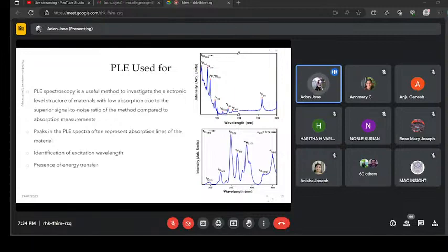Actually, from photoluminescence excitation spectroscopy, the first thing that we can interpret is that we can identify the excitation wavelength. It is very important because based on this excitation wavelength only, we can identify the pumping wavelength, and only based on that we can record the exact or correct luminescence spectrum from the material. Whereas in the other case, I already explained that there are certain materials having weak absorption bands. For that type of materials we usually use PLE spectroscopy for identifying which energy we have to supply for exciting that particular material.